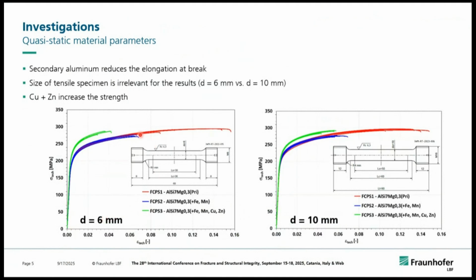And when we compare those results, we see the dramatic loss in the elongation, which is mainly related to the iron content. And we could see that for this FCPS3 alloy, where we had additionally copper and zinc, we had a slight increase in the tensile strength. But the main result here was a reduction in the elongation at break.